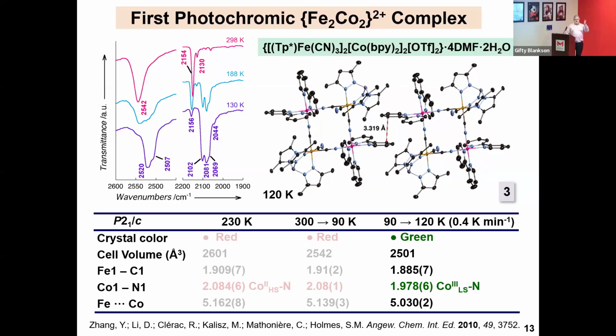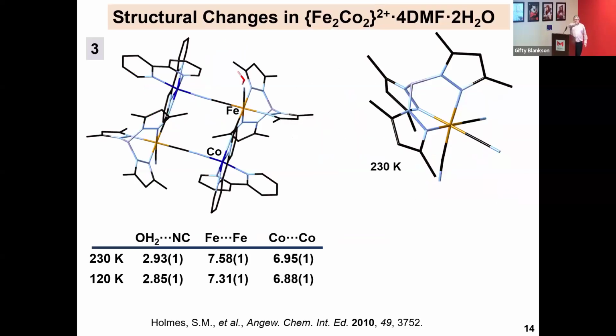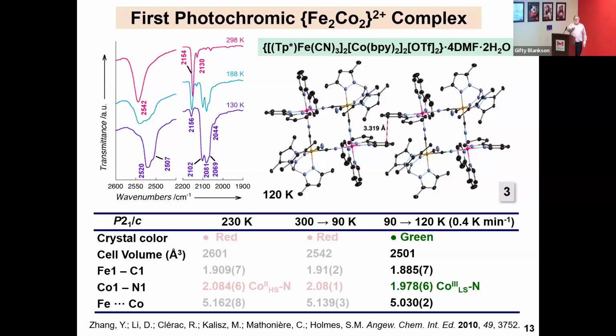What I haven't told you is there's a phase change around 120 K. Crystals shatter. You can see them explode under the microscope. What we had to do for this system, because we have these close contacts between the bipy rings, is that now we have molecules talking to each other. So when they breathe, any strain induced from bond elongation or contraction is going to be communicated. The problem here is that we had to quickly cool the material and then slightly titrate in some heat energy, allow it to relax. Sometimes the crystals still explode, but it's allowed us to get an X-ray snapshot of the two states.